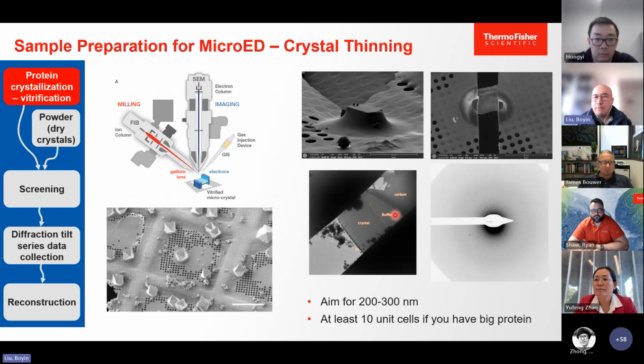For MicroED, as a rule of thumb, you have to have at least 10 unit cells in the lamella so that your sample is isotropic. Otherwise, with a very thin lamella, you get a very streaky diffraction pattern, which is not good for data processing. So basically, we want to choose 200. In our hands, a 200 to 300 nanometer lamella is the best.